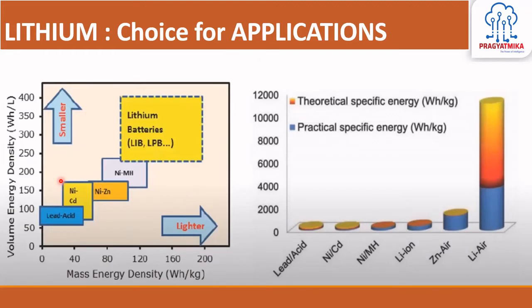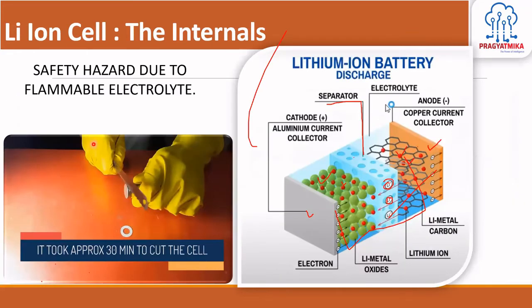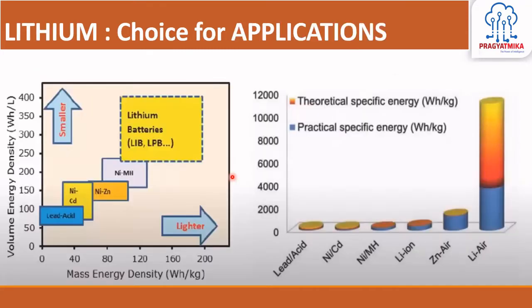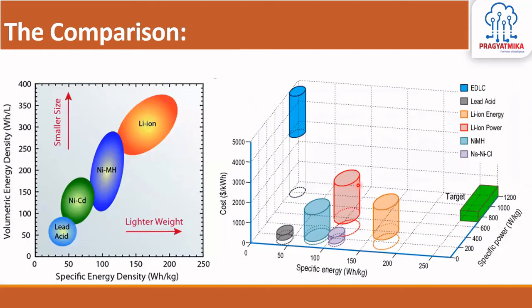So even if all these things are there, you can see that in a very small shape and size, just an 18 mm diameter and a 65 mm height, we can store around 6 Ah of energy. So that's why lithium remains the choice for the majority of applications compared to the other battery chemistries, because in a very small volume and very small mass, we can store lots of practical energy. And again, new chemistries are coming up, like zinc air or lithium air batteries, which will again have more storage compared to the current NMC or NCA battery packs. So that's why it remains the choice for the majority of applications.